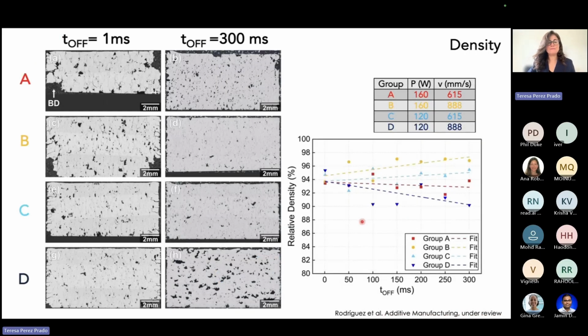Let us start with the density. So here again, I'm showing you several optical micrographs of cross-sections of the cubes printed, parallel to BD. And the different rows correspond to groups A, B, C, and D. The first column with no time delay and the second column with 300 milliseconds time delay. So we can already see that when we use D conditions, these are the low volumetric energy density conditions, if we, on top of that, cool the sample more, we introduce a lot of lack of fusion porosity. But in conditions B and C, qualitatively, it looks like the density even improves with the 300 milliseconds.